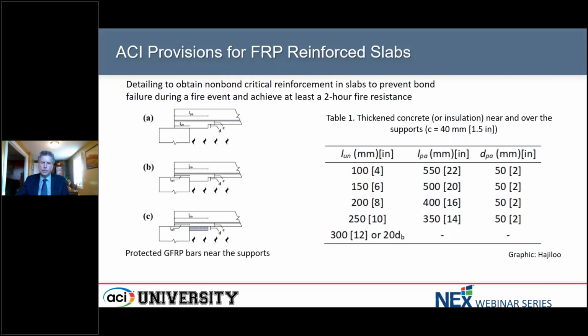And although in the code language there's not specific requirements for fire resistance, there is some guidance in the commentary about ways that you could achieve fire resistance by doing appropriate detailing. So the first thing that I wanted to mention is that one of the things we've recommended, if you can embed the GFRP reinforcement by about 12 inches or 20 bar diameters into a support or something like that, that should be adequate to ensure that you can achieve a 2-hour fire resistance of a slab without doing anything else.